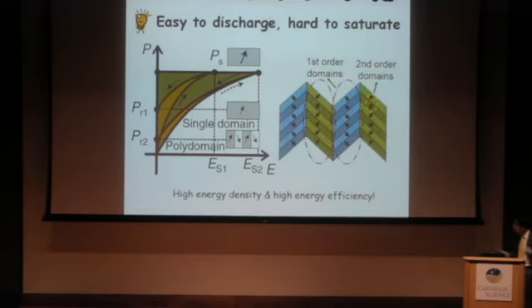So instead of this so-called first order, we can go a step further and create a second order. This is the domain that I showed you here. But if you can have even finer domain structures within these first-order domains, that could be even better, because as you go smaller, this so-called nanodomain structure can become very adaptive to the change of field.